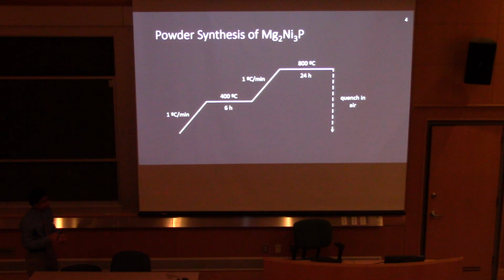We then leave it at 400 C to kickstart the reaction to go in the first place. It's kind of a driving force. Then we heat it up again slowly at a higher temperature to allow the reaction to go forward. It's like pushing it forward. And then finally, once this heating cycle is finished, we take out the tube and just leave it in regular air to rapidly cool down. Because if you cool it down slowly, it gives it enough time to form other byproducts which you don't want.